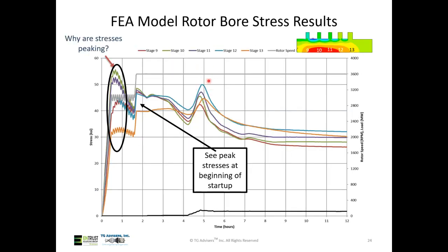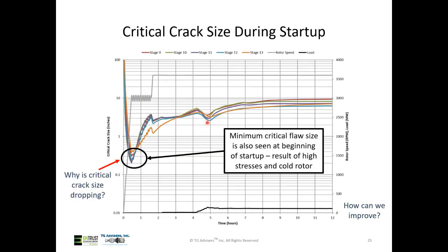Although I had that stress peak again around 5 hours, I have much larger critical crack sizes at that point. So I'm not at risk for failure at that point, which is why we don't like to spend a lot of time at that low speed hold, because if I was going to have an issue, it would have happened here.